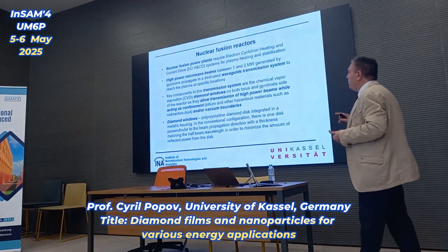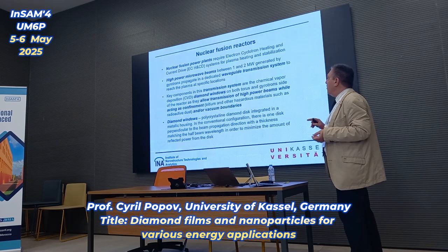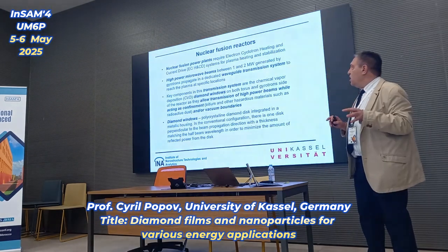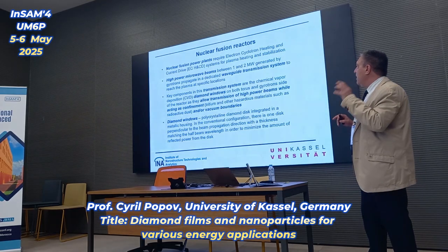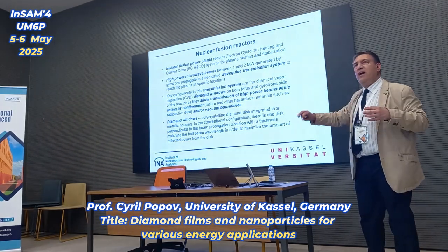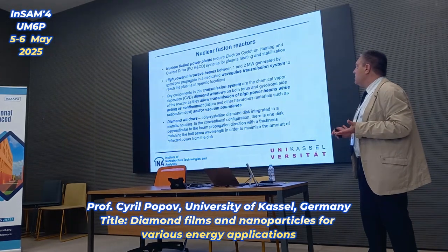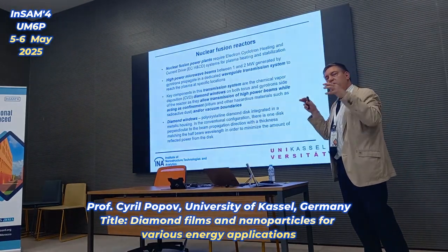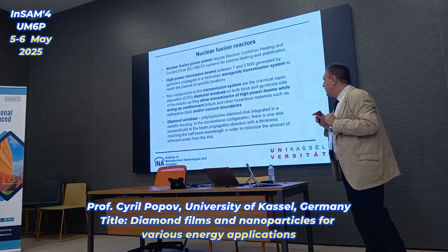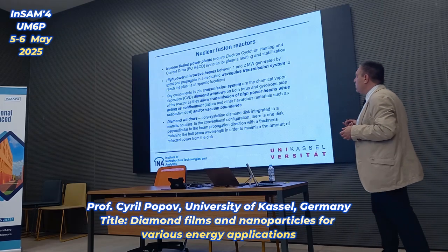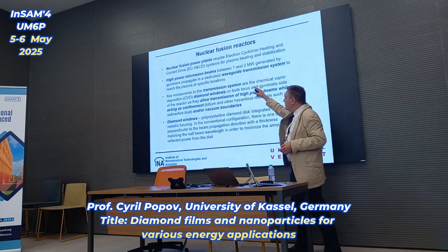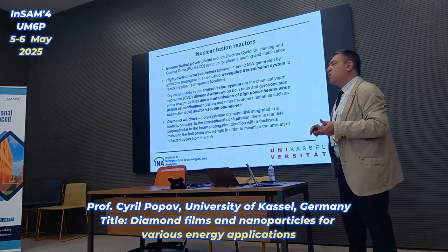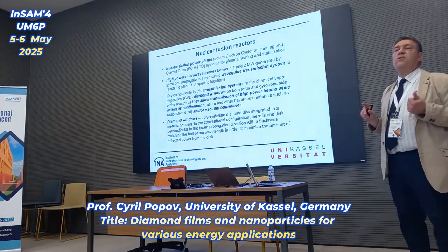Microwave beams of high power, 1 to 2 megawatts, are generated by gyrotrons, and they propagate along the waveguide transmission system to special parts where they have to heat the reactants. And the key component in such a transmission system are CVD diamond windows,